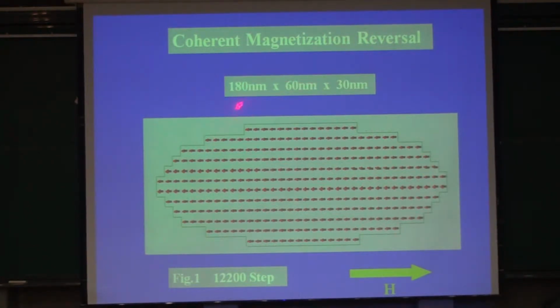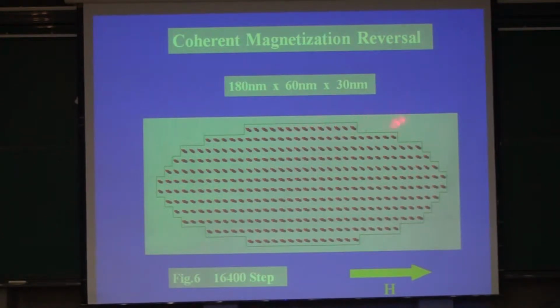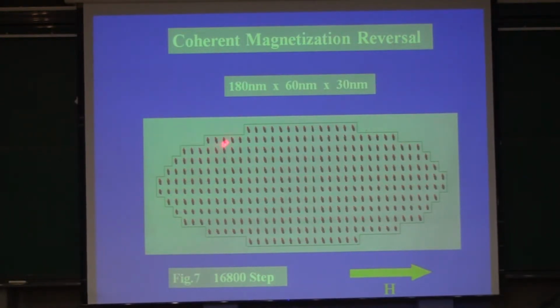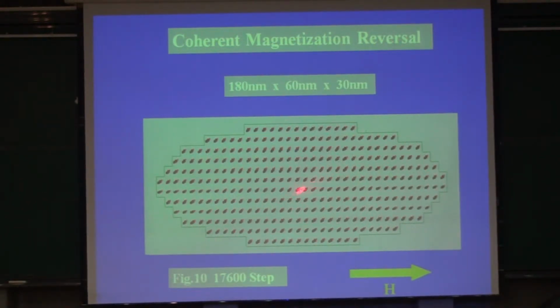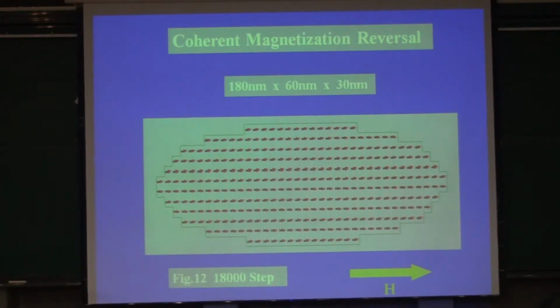But if you reduce the size by only half, such as 180 nanometers along the long axis, 60 nanometers along the short axis, and 30 nanometers in the z direction, and then you do the same thing, then the exchange force is dominant. Then they will reverse and lock together like a macrospin, all together. The shape effect is not so important, because the exchange force dominates. They want to reduce the exchange energy, so they lock together and reverse like this. So the size is quite important for everything.